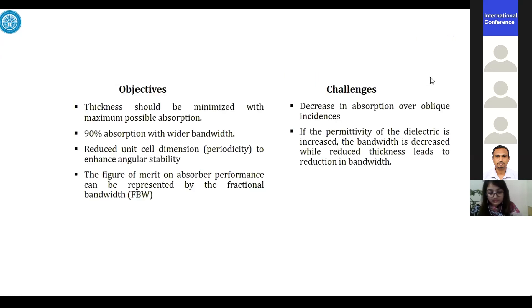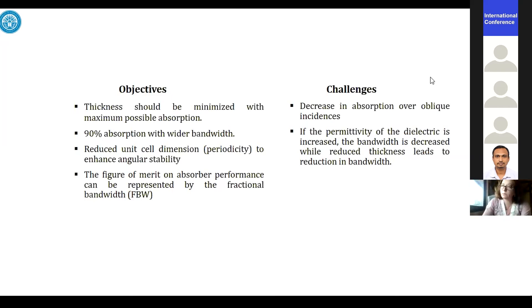There are certain objectives and challenges to keep in mind while designing microwave absorbers. For example, thickness should be minimum with maximum possible absorption, and they should have 90% absorptivity in the desired frequency band. The unit cell should have minimum periodicity and good fractional bandwidth, which is one criterion for checking performance. Challenges include a decrease in absorption as oblique angle of incidence increases, and that increasing permittivity decreases bandwidth, while decreasing the thickness of the absorber decreases the absorption bandwidth.